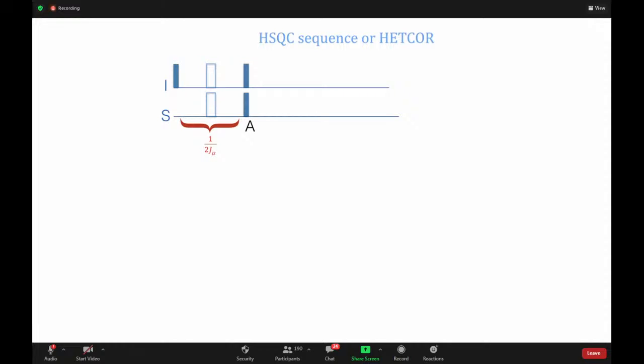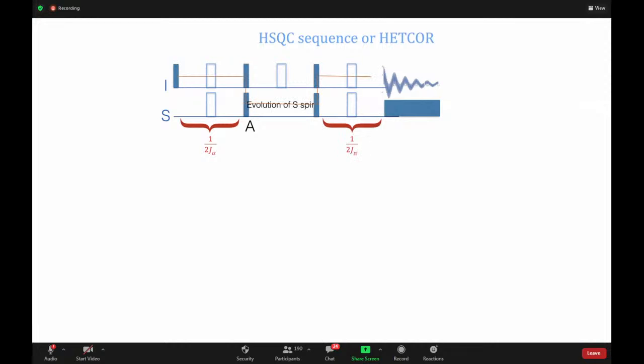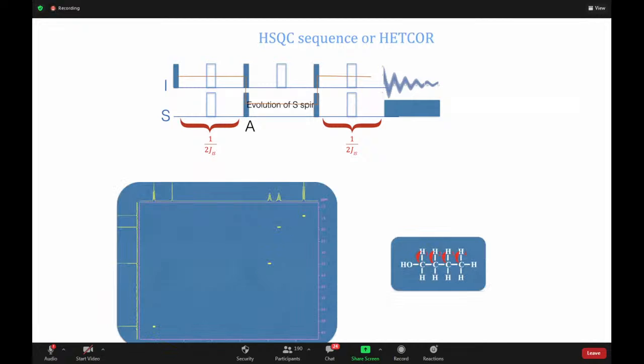You can also add one more INEPT step to make HSQC, and you get spectra. You get really highly sensitive spectra, because you are now starting with magnetization from the proton, and you're actually detecting on the proton. So here again, this is a COSY version, COSY-like, but it's heteronuclear. That's the only difference between HSQC and COSY. Also, we only see the cross peak and not the diagonal peak. So whatever peak that you see in HSQC spectra is all cross peaks.